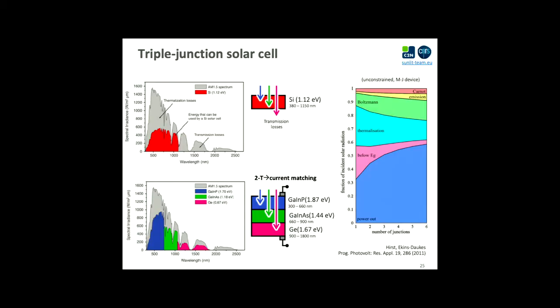Of course, if you limit yourself to one single junction, we've already mentioned these loss channels, mainly thermalization, so the photons with a very, very high energy that thermalize at the bandgap edges, releasing phonons, heat, or you have some transmission losses for the photons that have not enough energy to be absorbed because the energy is smaller than the gap. So we already saw this plot, so you already know how to read it. No need to explain it again. This is for a single junction, but if you go with a 3-junction, for example, you can dramatically reduce the losses by thermalization or by transmission, and the higher the number of junctions that you put on top, the lower are these losses.